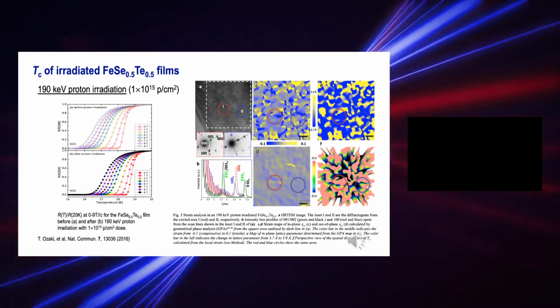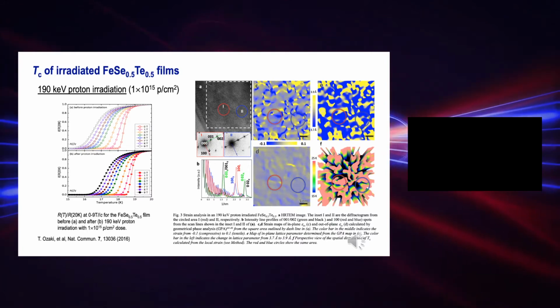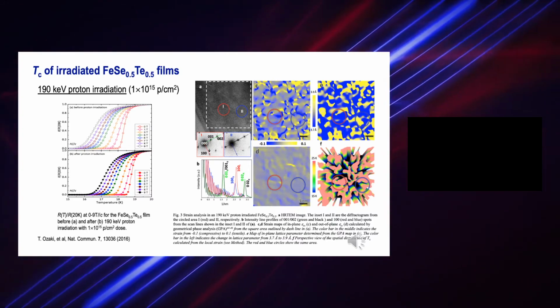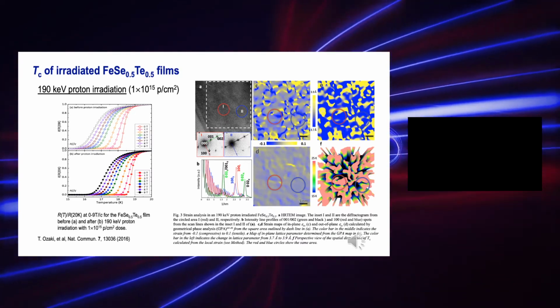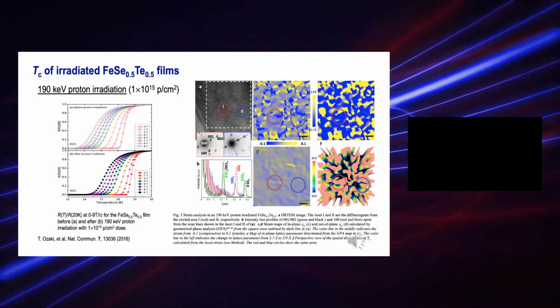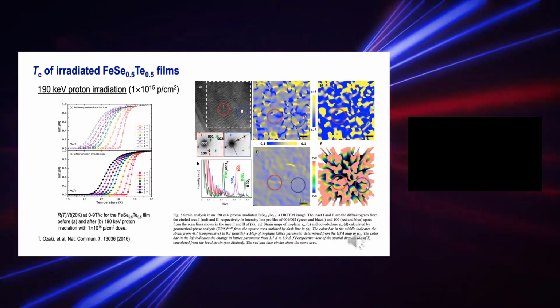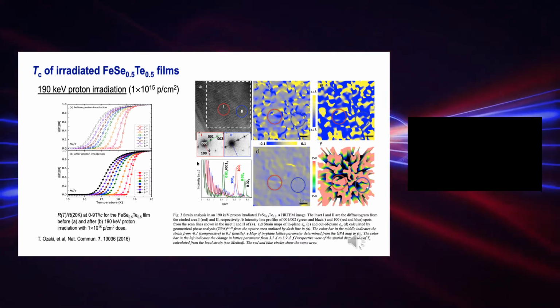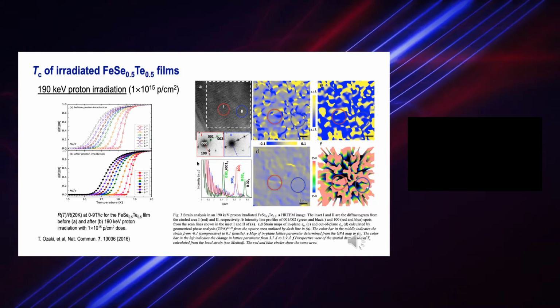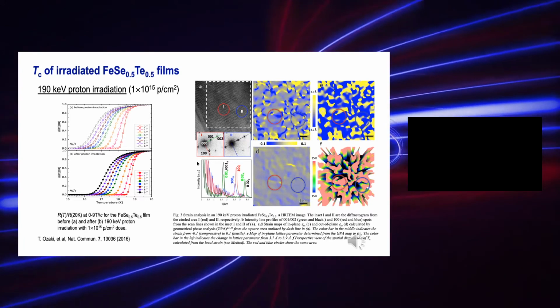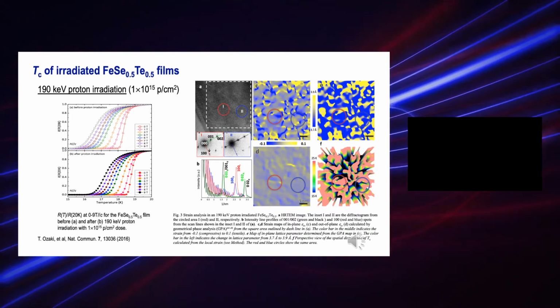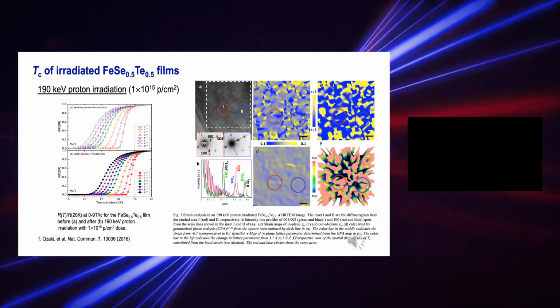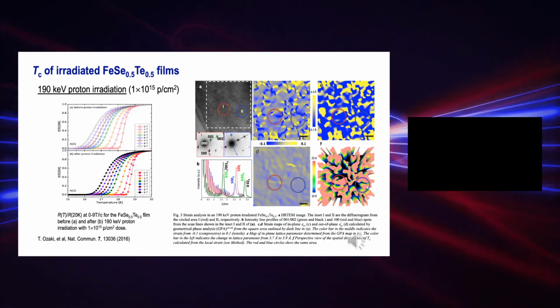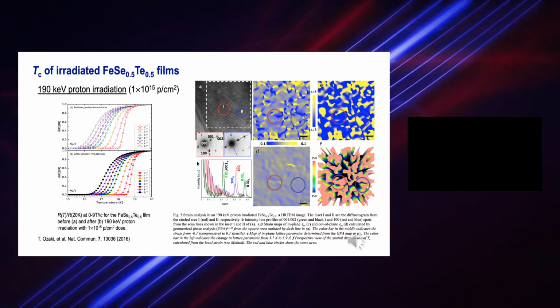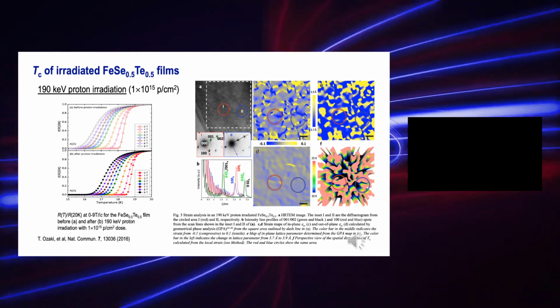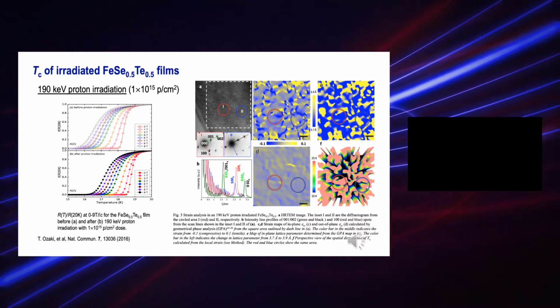Now, to understand the origin of the TC enhancement in these low energy proton irradiated films, we performed a detailed TEM structure analysis with strain mapping of these low energy irradiated iron chalcogenide films. A is a high resolution TEM image. The insets 1 and 2 are the diffractograms from the circled areas 1 and 2, respectively, one with defect, one without defect. The strain mappings are shown in figures C and D. Now, blue is a compressive strain, and yellow is a tensile strain. As you can see, at the nanoscale you have this compressive strain, which we know enhances the TC. So we believe that these created cascade defects with this nanoscaled compressive strain, and the proximity effect, gave the overall TC enhancement in these films.